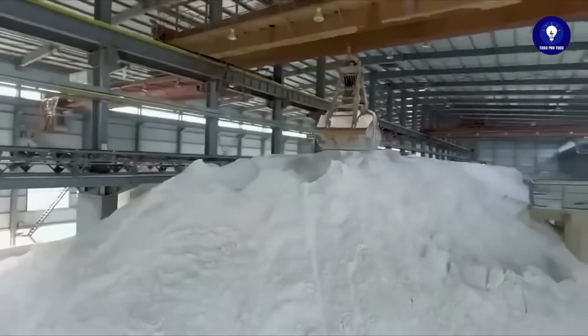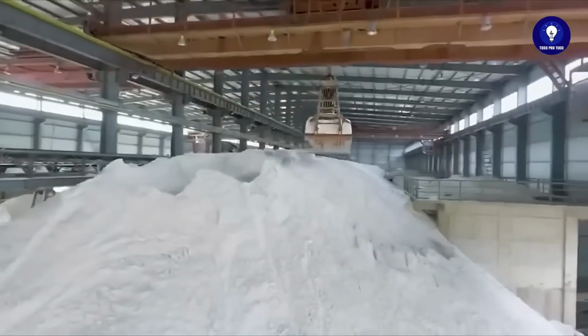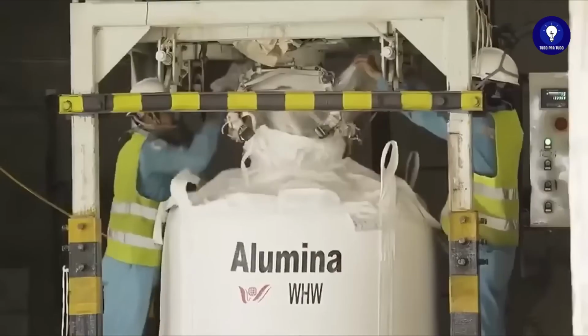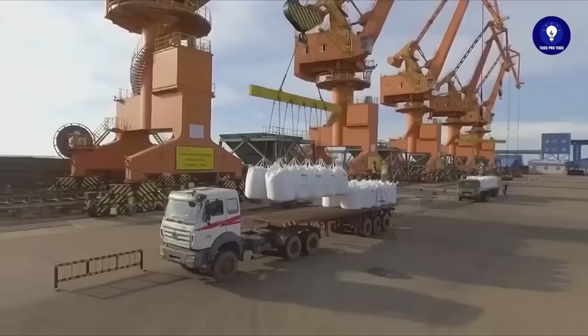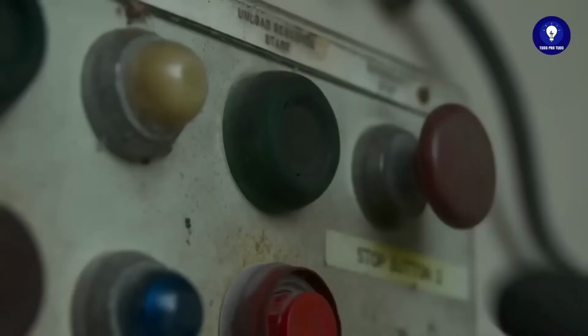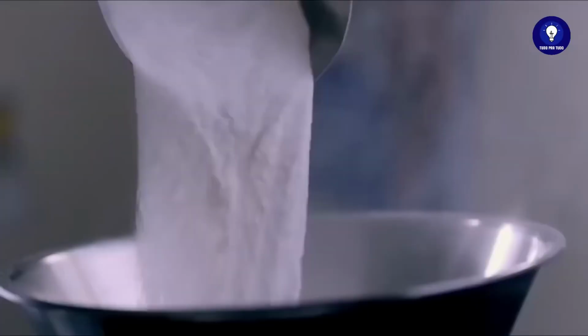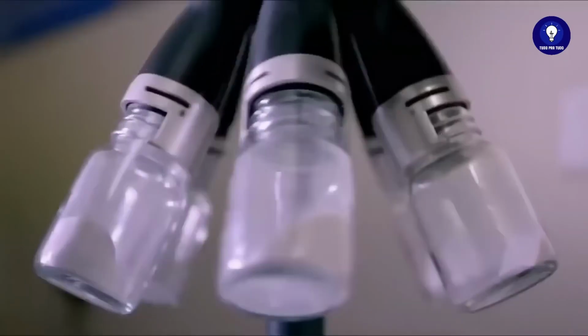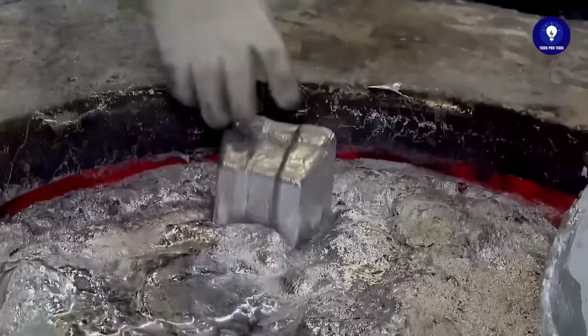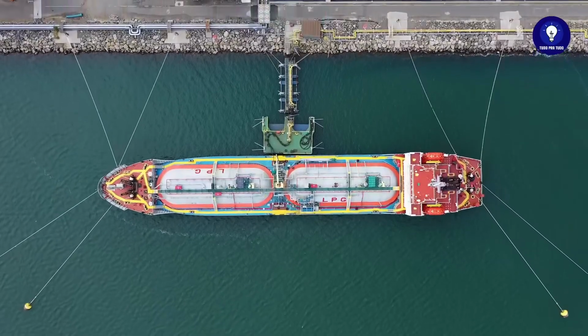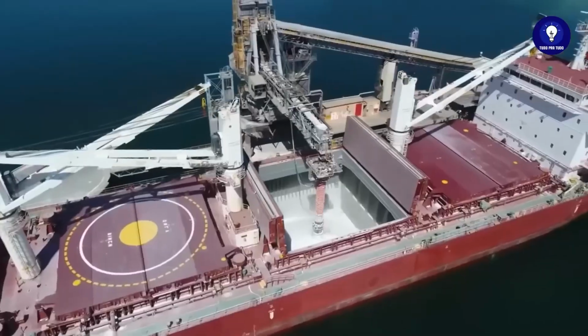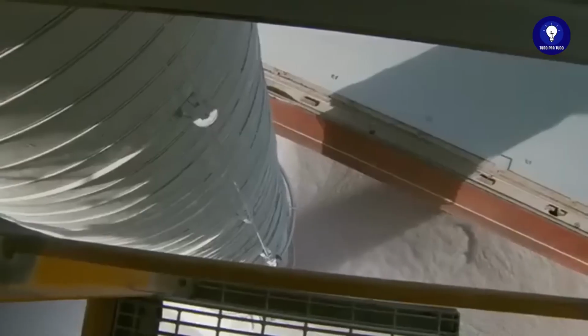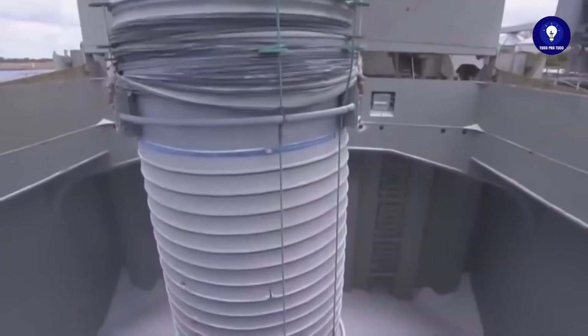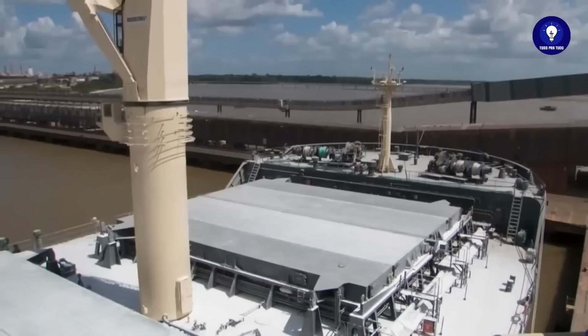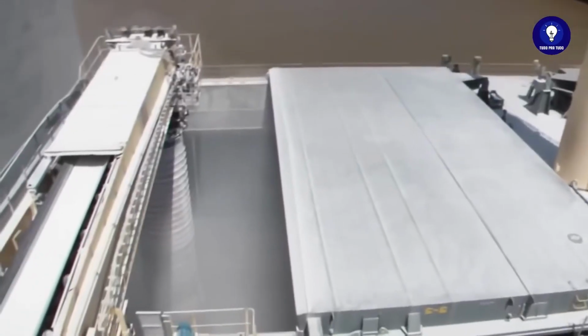The next step is to separate the aluminum from the oxygen. For that, the alumina is transported to an Alcoa production plant. A loaded ship leaves the port every 3 days. The alumina it brings will be transformed by the smelter into 30 to 35,000 tons of pure aluminum. Every 3 days, a ship arrives with about 1,500 tons of alumina. Next, all of its contents are sucked out by a kind of industrial super vacuum, which extracts about 300 tons per hour, emptying the ship in about 5 hours.